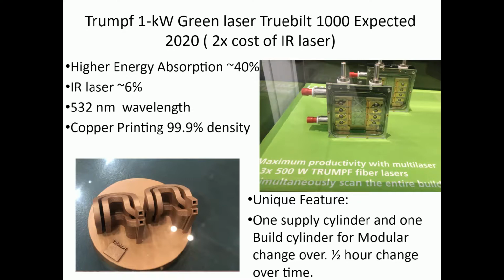The wavelength of the green laser is 532 nanometers. With the green laser, copper can be printed with 99.9% density. Higher density improves the conductivity of the material. Multiple laser heads can be used to scan the entire build area. Shown below is a copper inductor with internal cooling passages printed with a green laser system.